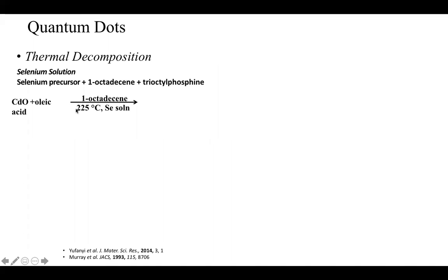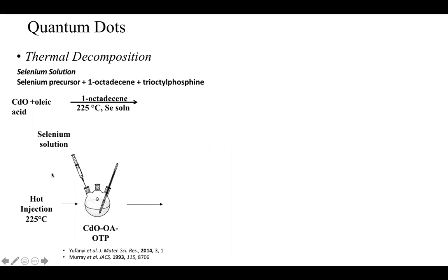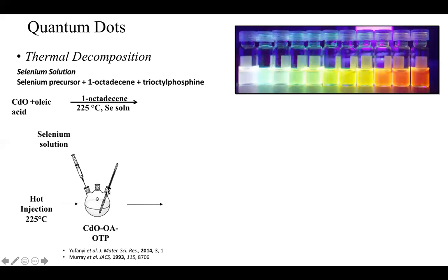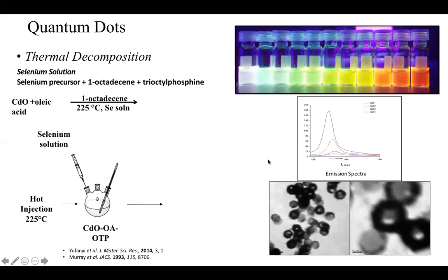One last method we looked at of synthesis was using quantum dots. So understanding how thermal decomposition as well, but quantum dots using a selenium precursor in the presence of octadecene and trioctylphosphine. We use a hot injection method. So at 225 degrees, we were able to inject selenium solution after cadmium oxide had reached ideal temperature. And based on that, we were able to see how we could produce different nanoparticles or quantum dots at those temperatures that were there, which led to a little hollow structure that we can see.